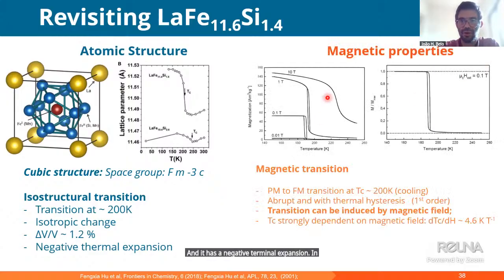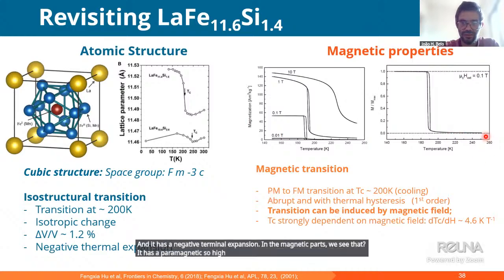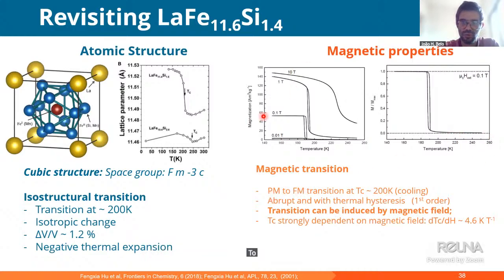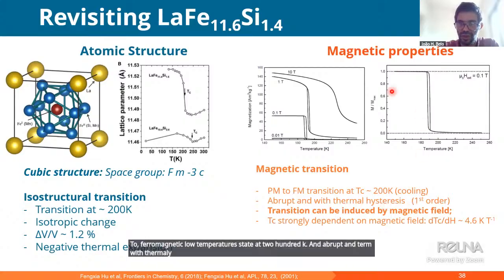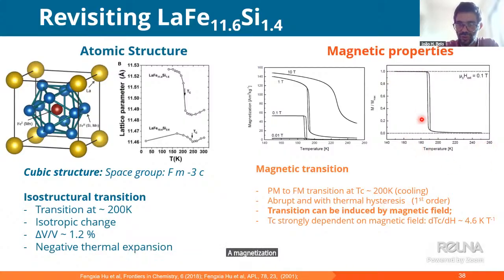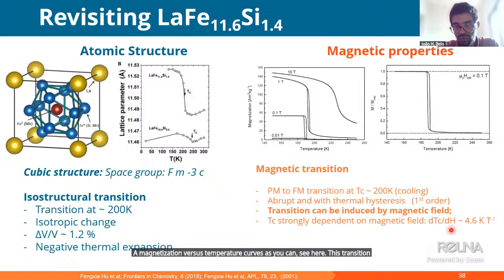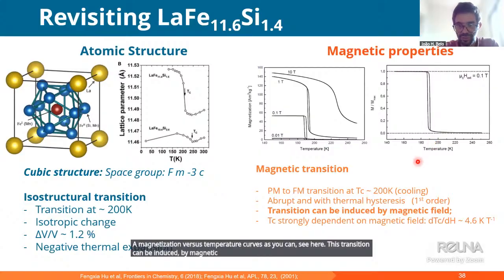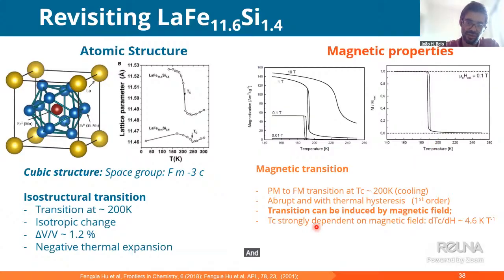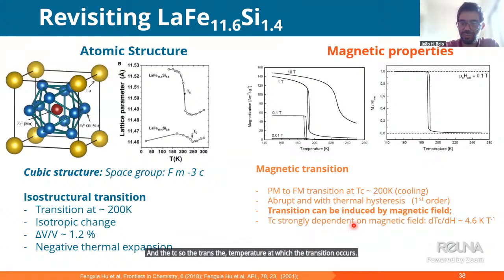In the magnetic part, we see that it has a paramagnetic state at high temperatures, transitioning to a ferromagnetic state at low temperatures, at 200 K, an abrupt transition with thermal hysteresis in the magnetization versus temperature curves, as you can see here. This transition can be induced by magnetic field isothermally, and the TC, the temperature at which the transition occurs, is highly dependent on the magnetic field in this given range.